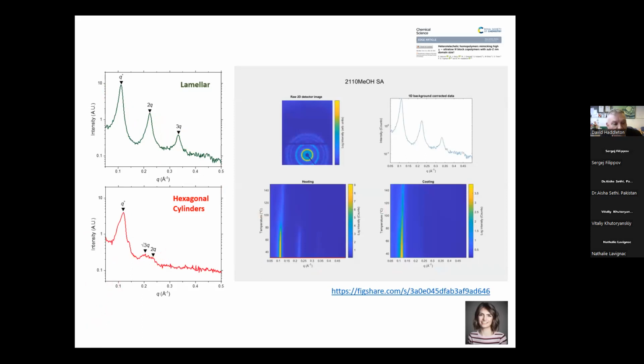And what we can do is, if I can turn off my laser pointer, I can even show you a video of this. So what we're doing now here in the spectrum in the top right, we are doing the SAXS in real time by changing the temperature. And when we get to about 80 degrees, we'll see that order disappears. So we go from lamella and the order goes away. Then when we cool that down, I'll just skip along a bit. So now we're cooling. And then when we get to below 80, we start to see some order come back, but the order now returns as hexagonal. So by the annealing, we change the way that the polymer orders by changing the polymer length.